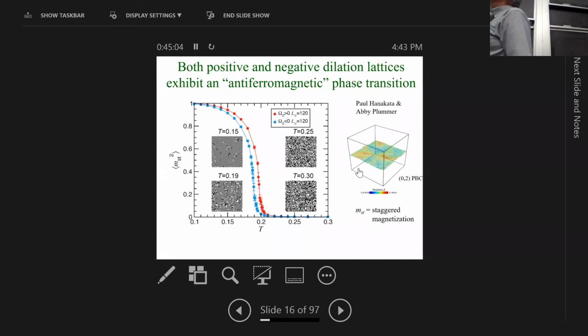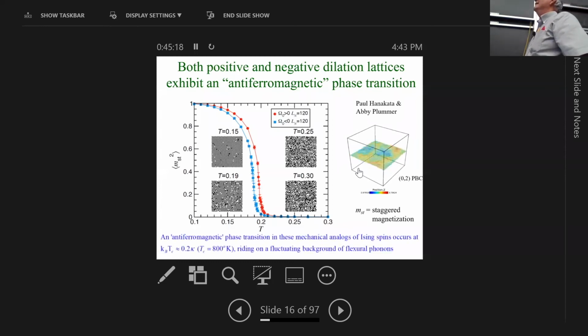And then at high temperatures, it looks like some kind of QR code where you put it in your iPhone to learn something interesting about your restaurant's menu or whatever. Anyway, it goes from this low temperature to this high temperature phase. And there is a phase transition that occurs at about 0.2 kappa. And if you estimate for some of these materials, it's about 800 degrees Kelvin. So you could imagine doing a vacuum experiment.